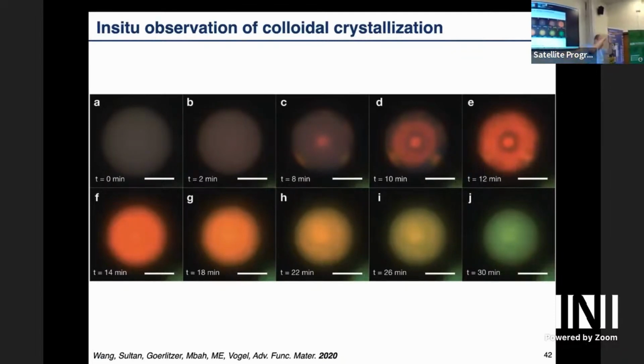And then in the layers on the outside, you form crystals with icosahedral symmetry. So you get an icosahedral templating from the outside. That's what we see here. Then this icosahedral templating moves inwards, it grows towards the center. When we are here, this comes from the growing crystal here. And then eventually it grows all the way to the center. You're somewhere here, and then, because the crystal is denser, it melts again on the surface. You're here, and then the crystallization process is completed.